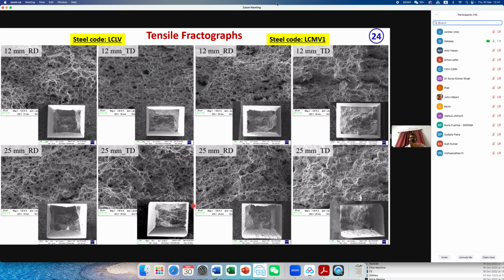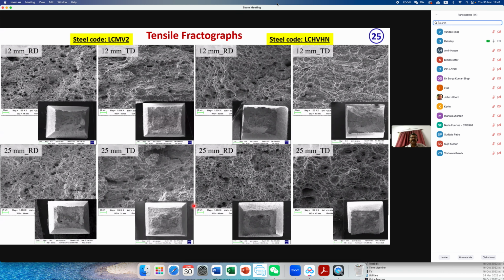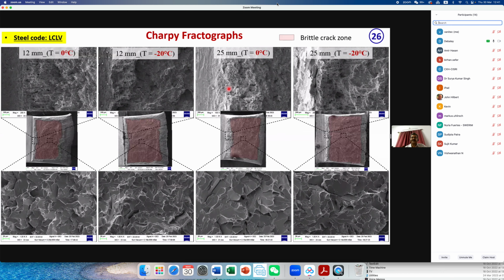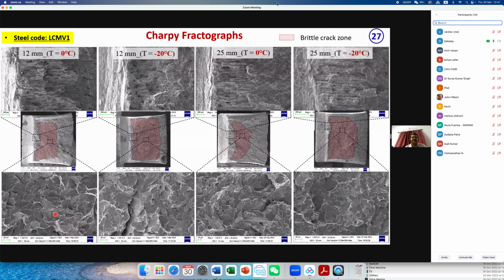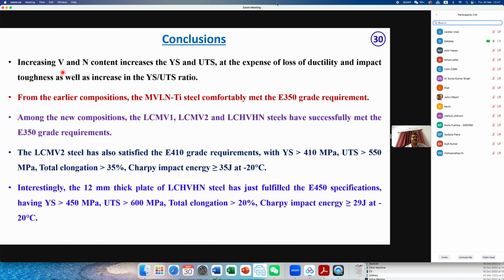So we expect, I'm quickly going through this slide. These are the fractographs. Under the notch root, we see ductile fracture. Sometime at -20 at the depth, we are finding some cleavage fracture. So all these slides we have shared. And so we have really found the beneficial effect of vanadium and nitrogen addition. Even with 100 ppm nitrogen, we found that it is giving good property, increases YS and UTS at the expense of some loss in ductility and impact toughness.